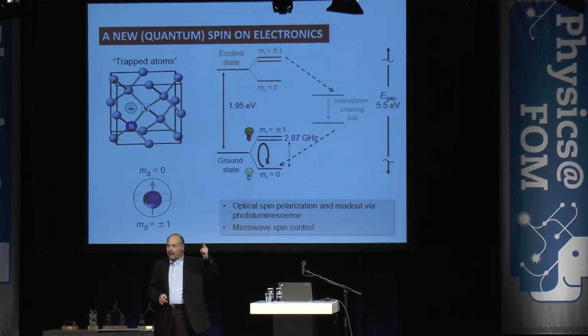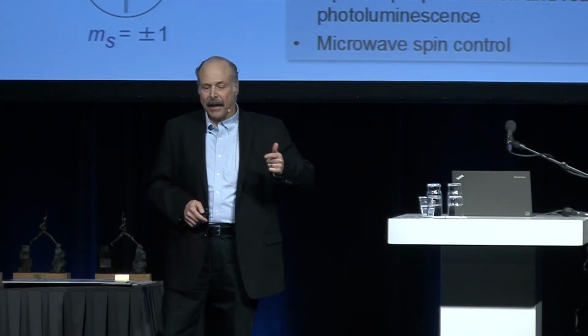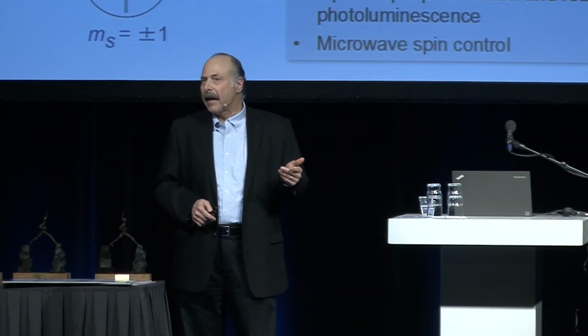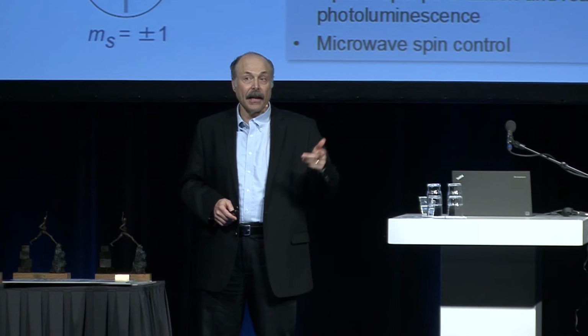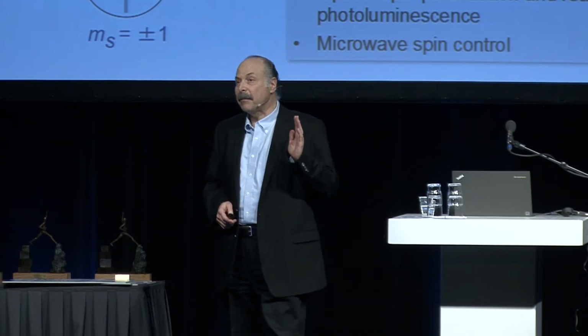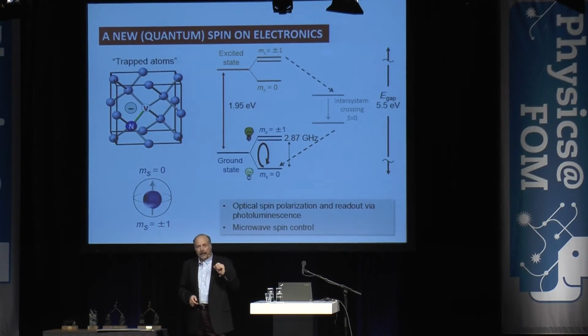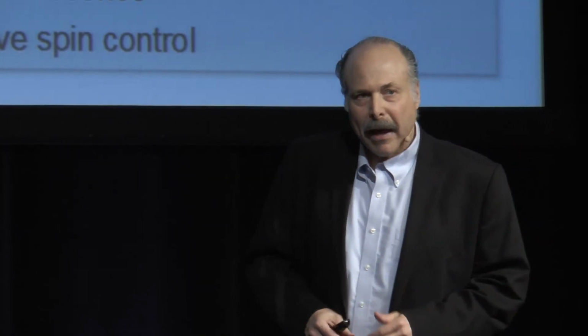And the system will simply relax by itself through a metastable state into a ground state that, as you repeat this over and over again, called a cycling transition, ends up with a spin polarized electron in this ms equals 0 state. And all of that's done within a 5.5 electron volt band gap, which means this is very robust at room temperature. 5 eV is a very big temperature scale. So that's amazing. It means you take a diamond, you just illuminate it with unpolarized light, and you end up with a polarized electron.